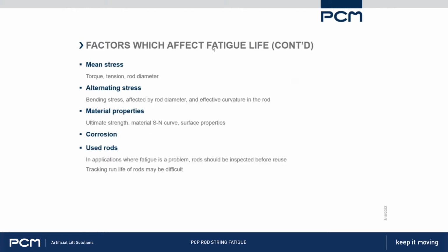Just looking at these in some groups. So mean stress, very important, of course: the torque, the tension, the rod diameter. The alternating stress, that's the bending stress in the rod, affected by the diameter and that effective curvature. Material properties, so the SN curve basically, and the surface properties as well. So one thing I'll mention there is that most sucker rods that you'll buy, other than polished rods, are hot rolled. It's a process in the manufacturing process they used to make them.